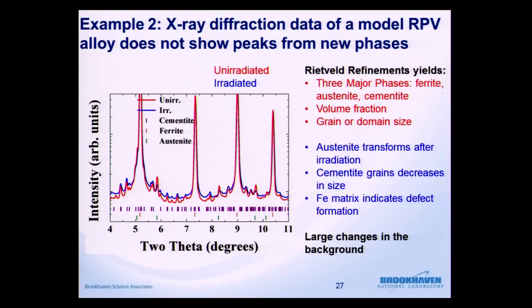So in this case, in the red, we had 3 major phases. We saw ferrite, austenite, and cementite. We were able to fit a model to the data and determine the volume fraction of the phases and get the grain size. Then we also did the same thing with the irradiated material. With the irradiated material, we see that one of the phases, the austenite, greatly decreases. The amount of it decreases after irradiation. The cementite grain decreases also. And the iron matrix indicates that defects have been formed.